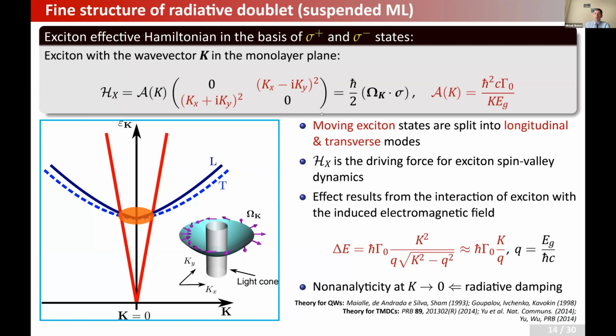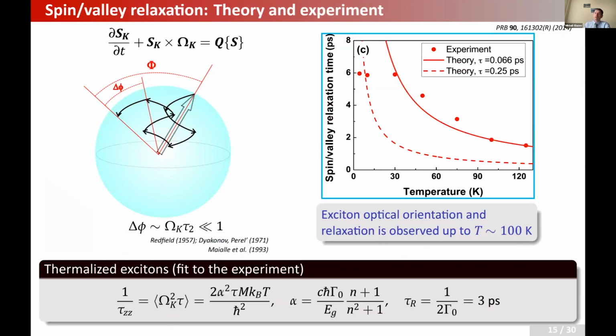We have this effective magnetic field, and this effective magnetic field produces a lot of effects on the exciton dynamics. For instance, it acts as a driving force for exciton spin-valley dynamics, and one can indeed observe it in experiments. You create excitons, say, by circularly polarized light, and then you measure depolarization. You measure the spin-valley relaxation time, in our case, at which exciton circular polarization would vanish. I'm showing you here the results of our collaboration with our colleagues from the University of Toulouse in France, who measured the exciton spin-valley depolarization by using a pump-probe technique.